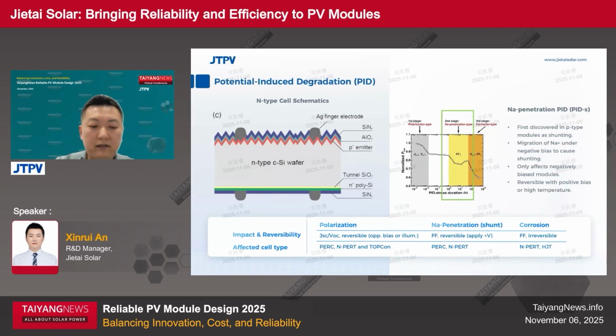The second stage is the sodium penetration type PID, or the shunting type PID-S. It is equivalent to the shunting problem initially discovered in p-type modules. The sodium ions released from the soda-lime silicate glass or some other contaminants migrate under the negative potential between the cell and the grounded module frame. And over time, they can penetrate the module encapsulant and even the cell anti-reflection coating layer to reach the emitter, therefore creating the shunting path and causing fill factor reduction. And PID-S only affects negatively biased modules, so it can be recovered by simply applying a positive bias or subjecting to high temperature.